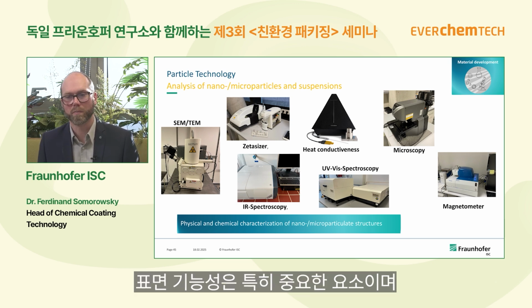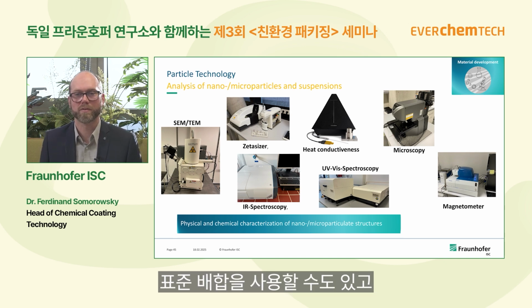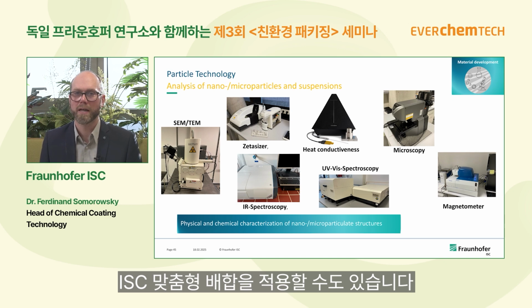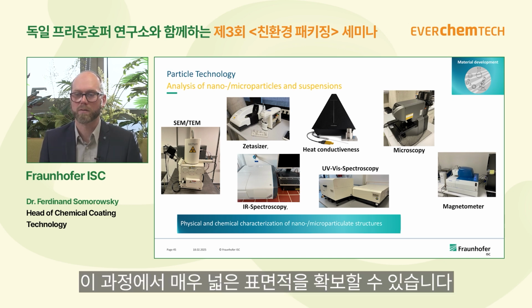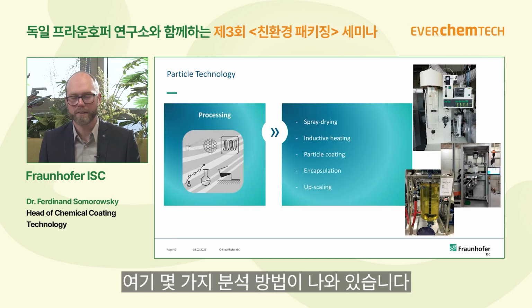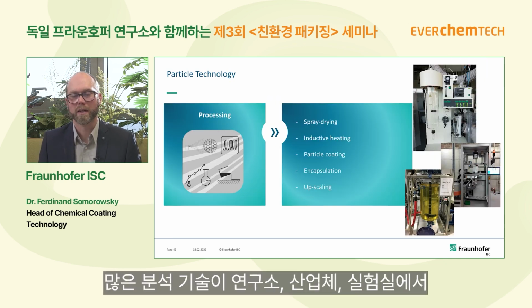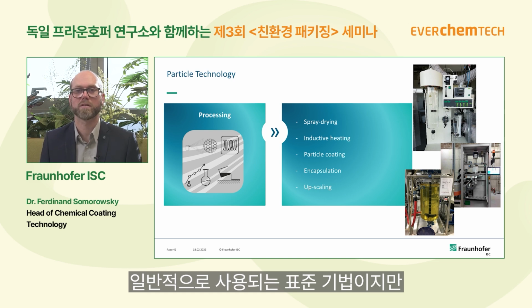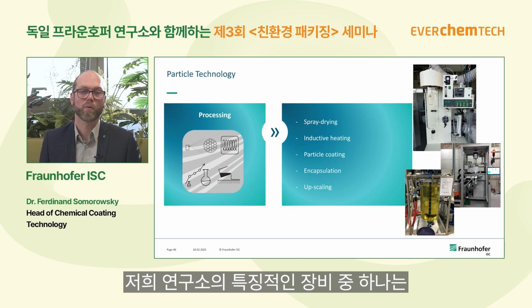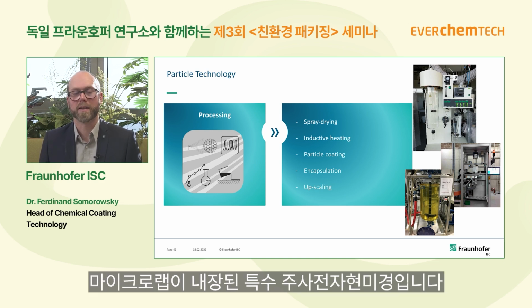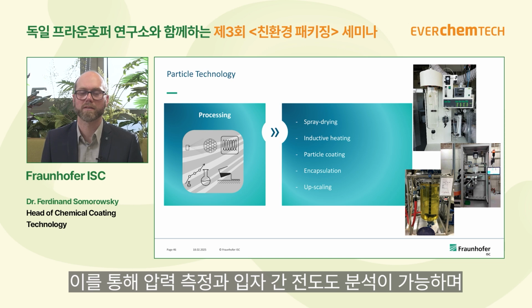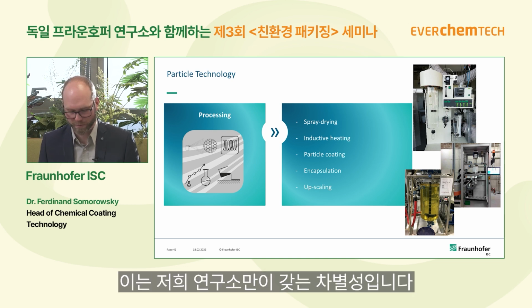So surface functionality is very important, and you can equip this with a standard formulation, but also with a Fraunhofer ISC formulation, and overcoat each of these particles. A special thing is that you have a very, very high surface area, and for some processes that is very important. Here are some characterization methods shown. I would say a lot of these are not very special and are very common in many laboratories or research institutes, or also in industry. We have, for example, a special SEM, scanning electron microscope, where we have a micro lab in the SEM, so we can do pressure measurements or measure the conductivity between different particles, and that is very special in our institute.